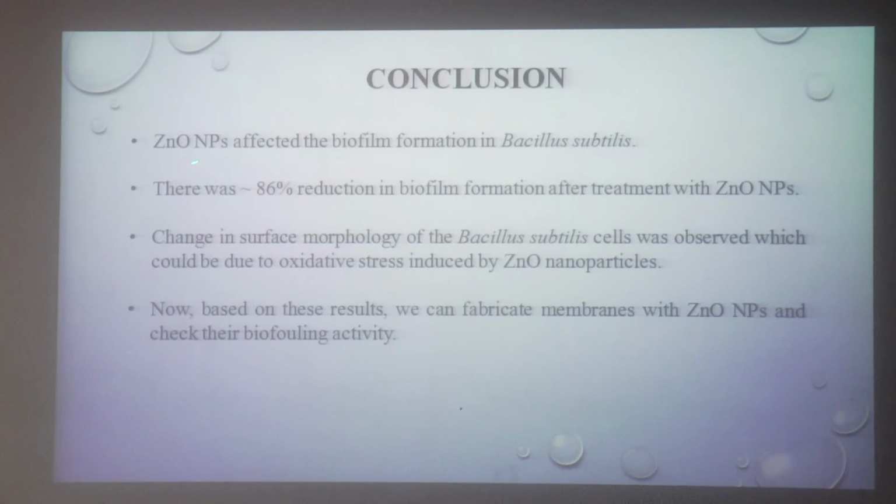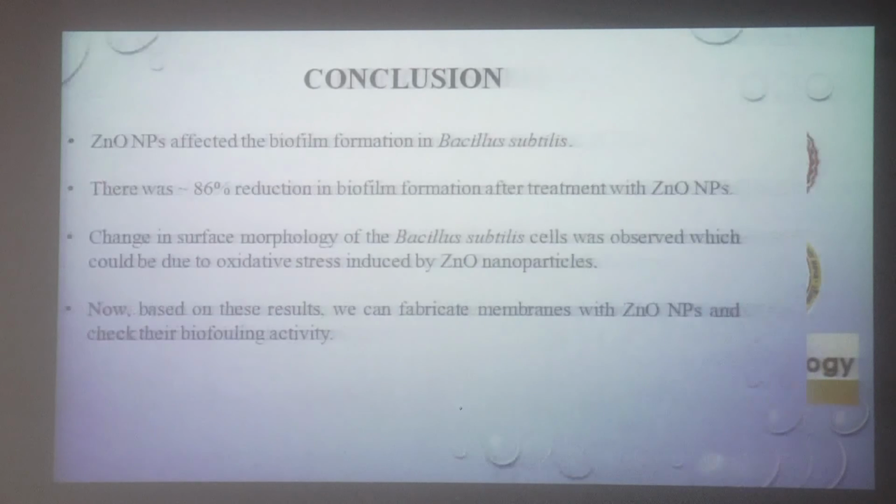Now at the end, I would like to conclude that ZnO nanoparticles are affecting the biofilm activity in Bacillus. Around 86% reduction was observed, and the morphology was changed. Based on these results, we are about to fabricate membranes with ZnO nanoparticles and we will check the biofouling activity.